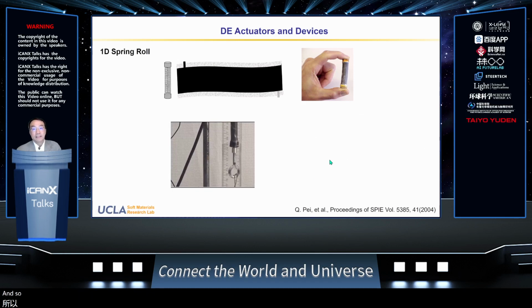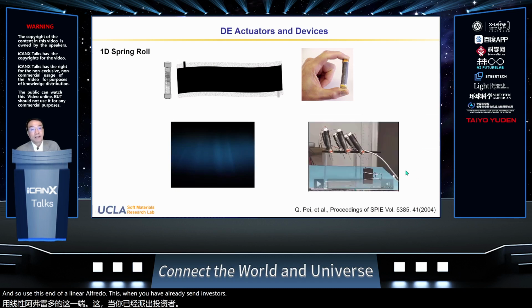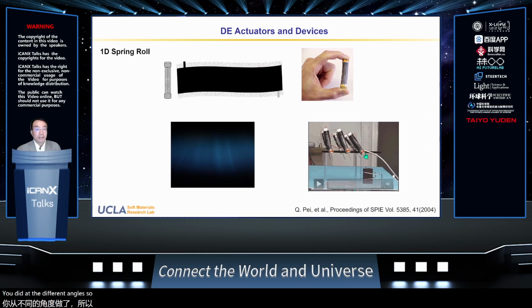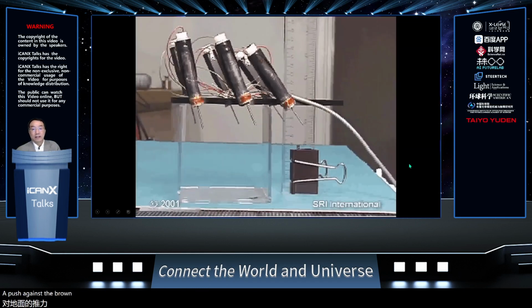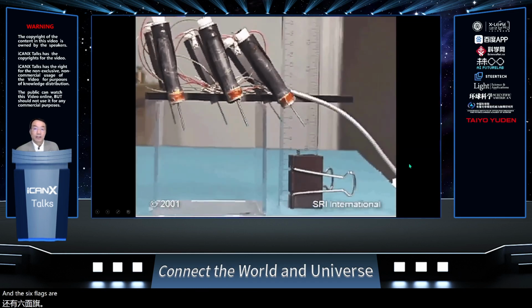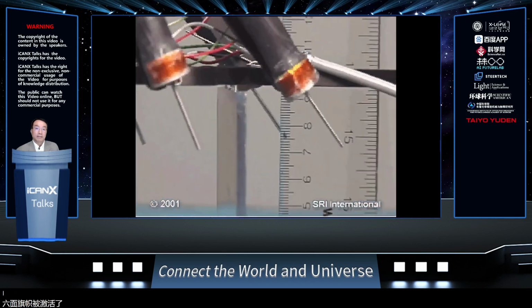Okay, so we use this kind of linear actuator, which extends in length when you apply voltage, and we can design a simple robot, as the one shown here. It has 6 legs. If you look closer, you will see that the 6 legs are tilted at different angles. The one to the front, or to the left here, is to lift the height. The one to the right is at a larger tilting angle, so this is to push against the ground. And the 6 legs are actuated in 2 tripod modes.